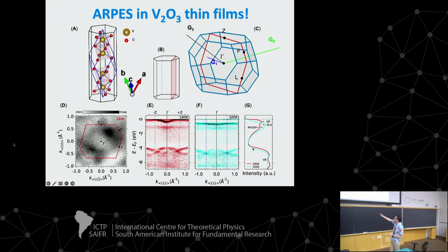The first glimpse of the answer is that, so this is energy as a function of momentum. In the metallic state, we see the electron-like pocket around gamma as in previous results, and the non-dispersive or weakly dispersive Mott-Hubbard band. And you see in the insulating state at 100 Kelvin, the spectrum changes completely. We still have this Mott-Hubbard band, but we have a new state appearing here. It is almost localized. It shows a little bit of dispersion that is different from the Mott-Hubbard band. We call that state a quasi-localized state.